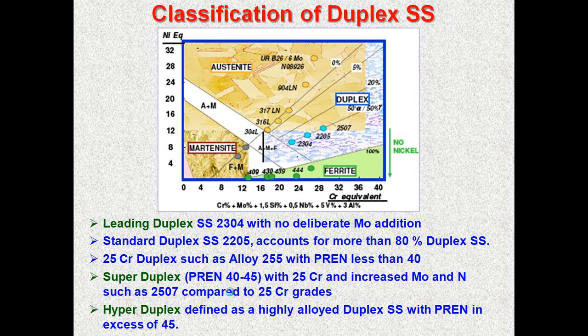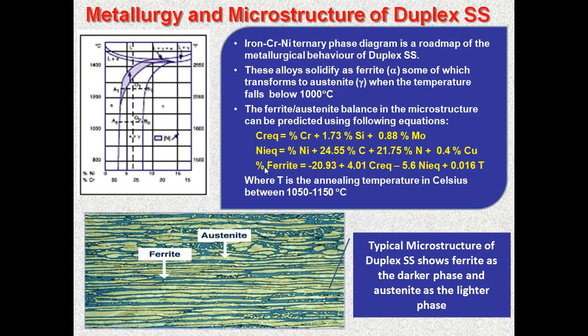The beauty of duplex stainless steel is that it starts from a primary ferrite solidification. It goes through a ferrite-austenite zone where it gets appropriately separated into 50% ferrite and 50% austenite below 1000 degrees when it is being cooled. If you want to get this 50-50, you have to control the chromium equivalent and the nickel equivalent following the percentage ferrite, so that you get only 50%. It is typically a microstructure where ferrite is the darker phase here, and the lighter one is the austenitic matrix.